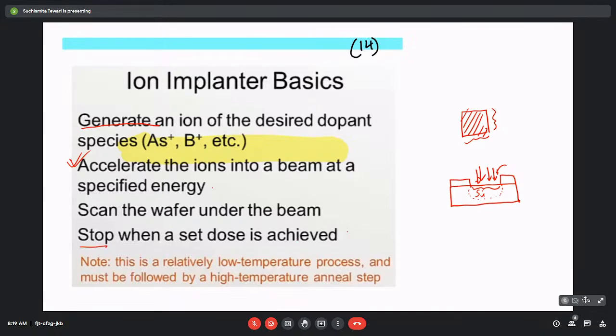Now remember one thing, this ion implantation itself is the step just before the annealing. This entire mechanism of ion implantation is a low temperature process, but this must be followed by a high temperature anneal step. So ion implantation basically is a two-step process. At first we have to do the simple ion implantation, and then we have to follow it with the anneal step, which is a high temperature process.